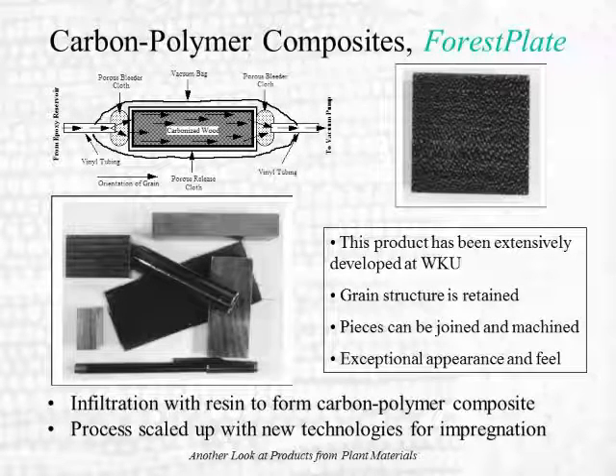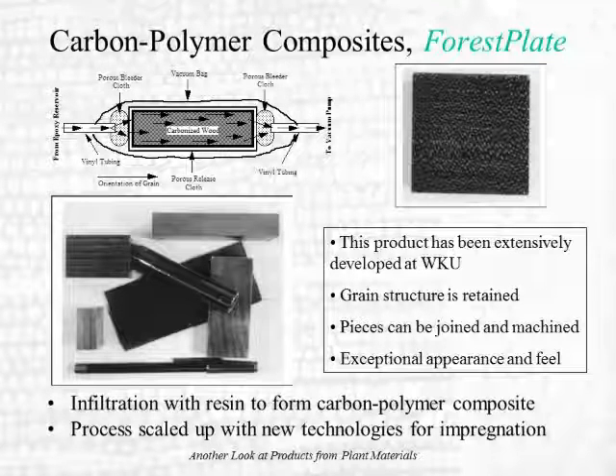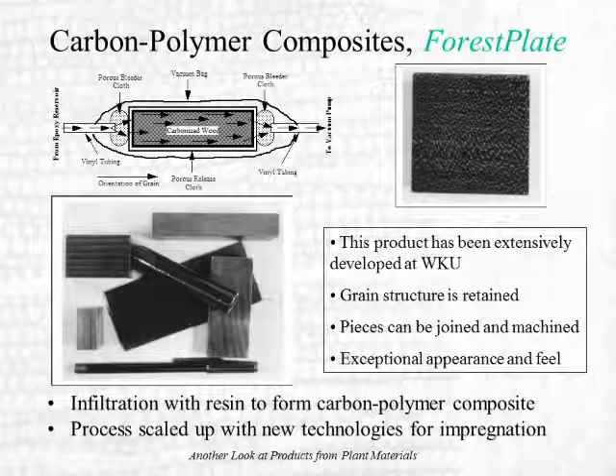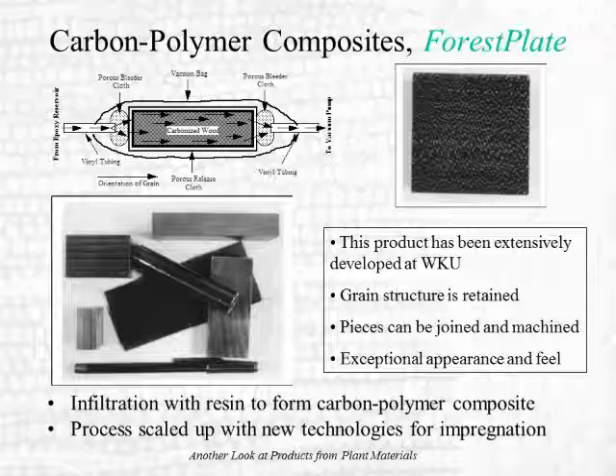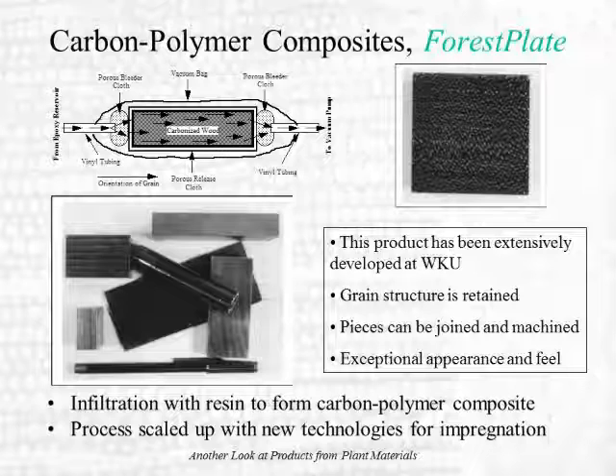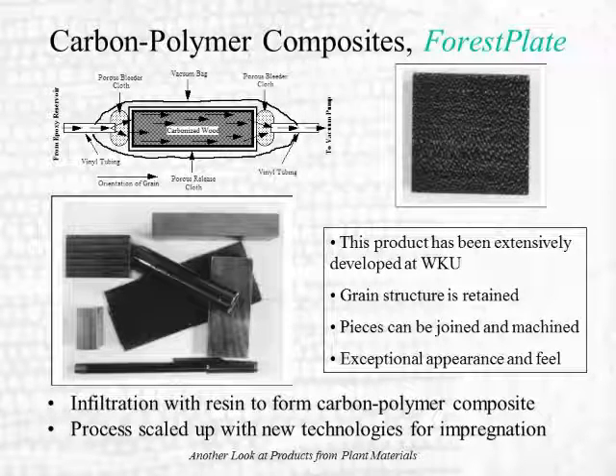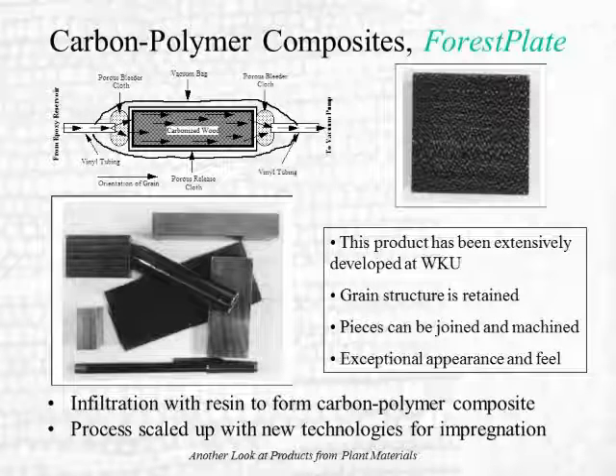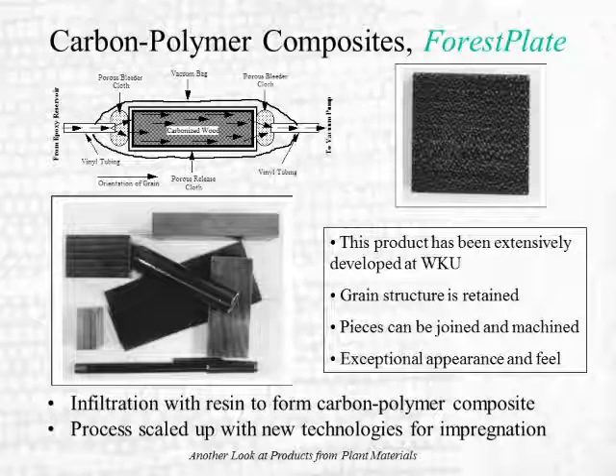There are many ways of making carbon polymer composites, and the traditional ones are fiber, carbon fibers with a variety of precursors used to make them, whether it be pan or pitch fibers, and then those fibers are then glued together with a matrix, and the fibers are there to carry all the structural loads. The matrix just glues them together. However, in this case, it's a carbon polymer composite by virtue of the fact that it has 2 phases. It has a carbon phase and a plastic phase. The carbon phase is not there because it has as great structural integrity as a nicely engineered carbon fiber.